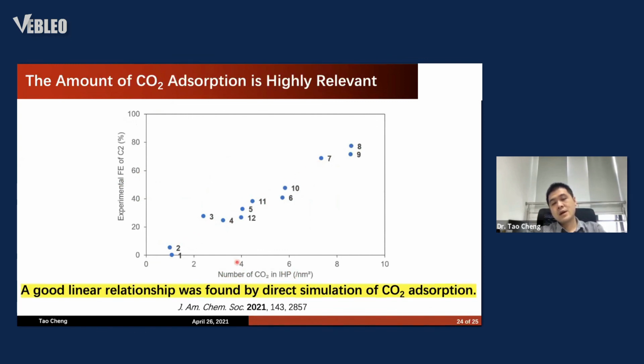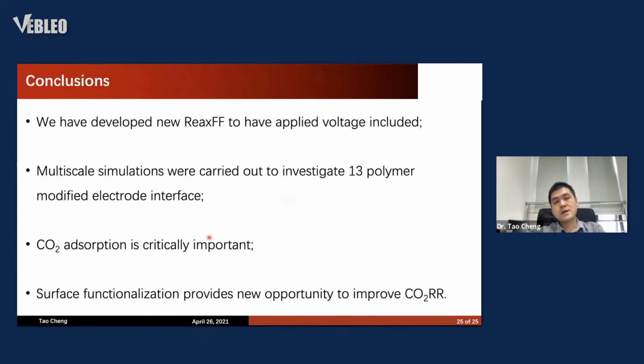This means that the CO2 adsorption is really relevant for the performance. To take away, we first developed a new reactive force field that includes the applied voltage. We also carried out multi-scale simulations to investigate different polymers on the electrode interface. And we found that the CO2 adsorption is really important. We think surface functionalization is really a new opportunity to improve the CO2 reduction performance.